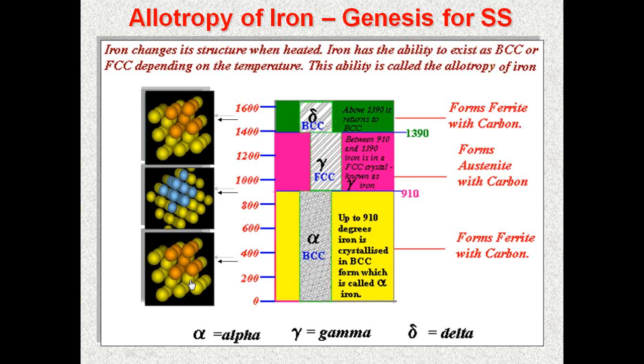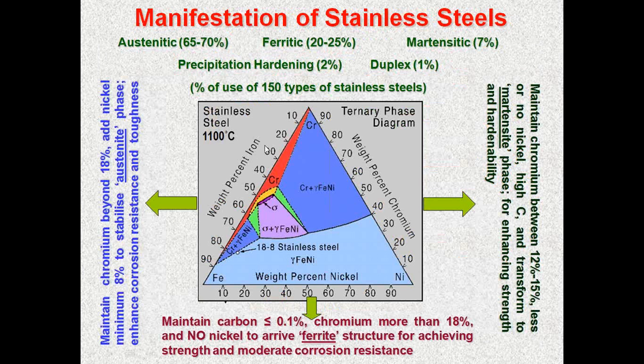Now, depending on the structure, you have a classification of the stainless steels. It can be a ferritic stainless steel or an austenitic stainless steel, and you also produce martensitic stainless steel by phase transformation. Now, I have given you a ternary picture of iron, chromium, and nickel. You can see here the percentage of iron, percentage of nickel, and percentage of chromium. And if you look commercially, there are about 5 different types of stainless steels available in the market. The austenitic stainless steels, which are predominantly 65 to 70%. The ferritic stainless steels, 20 to 25%. The martensitic stainless steels, about 7%. Precipitation hardening stainless steels, about 2%. And duplex stainless steels, about 1%.